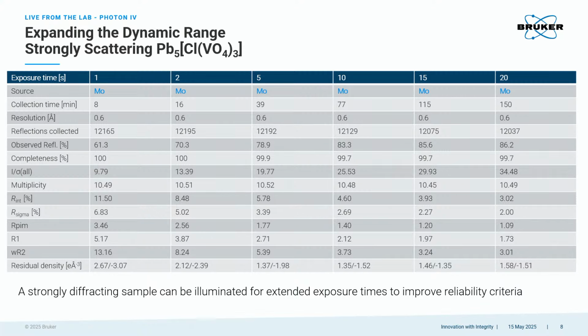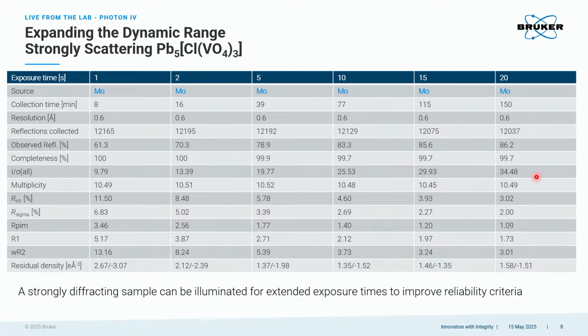I don't want to go too much into this, but what I want to show here is that you can blast this crystal. Basically, you get a good data set in 8 minutes from 1 second exposure times, but then you can push it. You see the last column, that's 20 seconds. And the nice thing is, yes, eventually we'll lose a couple of reflections. Maybe I turn on a pointer here. You lose like 3 reflections, but you significantly improve the data. And this is really collected in sensitive, photon counting mode with the detector. So that just shows the expanded dynamic range of the detector, especially compared to the Photon 3. That's maybe one of the things I'm most excited about with this detector, the large dynamic range.